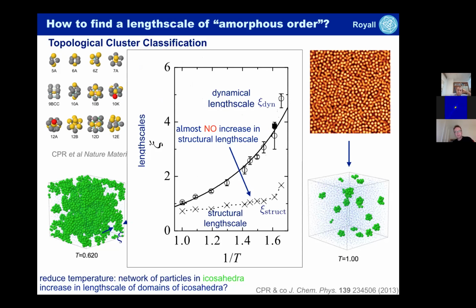However, there is a problem. And the problem is that the dynamic length scale that I mentioned of the brightly colored regions, so to speak, in the previous movie, this dynamic length scale we can determine is totally different to the structural length scale. And if these regions of icosahedra that I've denoted with this C with the green image on the bottom left, if they were responsible for the dynamical slowdown, these two length scales should increase together. That's not happening. So in this case, the emergence of the icosahedra is interesting, but it is not the sole reason for the change in viscosity of this material.